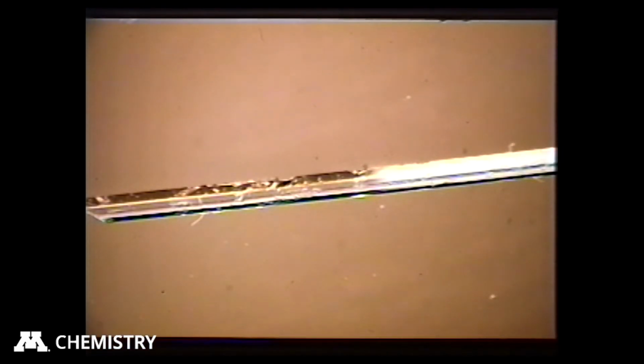Okay, now I'm going to show you a little different effect here. This is a big single crystal of tribenzoyl methane. We were very interested in this crystal structure, and the crystal quality is quite good. The crystals grow too long, and every time we tried to cut them, they would shatter into a bundle of hairs. So we really couldn't cut them. What we tried to do was to mount this crystal and just put the tip of it in the X-ray beam to get the crystal structure.